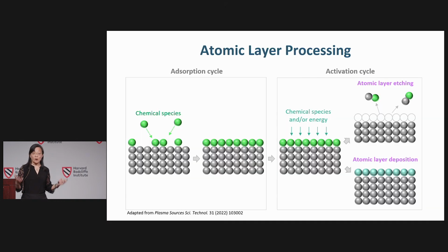We use atoms and molecules to our advantage to do surface chemistry. Let me try to explain this. We start these processes typically with an absorption cycle. I use these green spheres to illustrate the gas molecules coming down onto the surface, which is shown in gray. The chemistry between these two types of molecules is specific. So once you form a monolayer coverage on the surface, the reaction will not continue. They will not accumulate on top. So you have one atomic layer of material to work with.